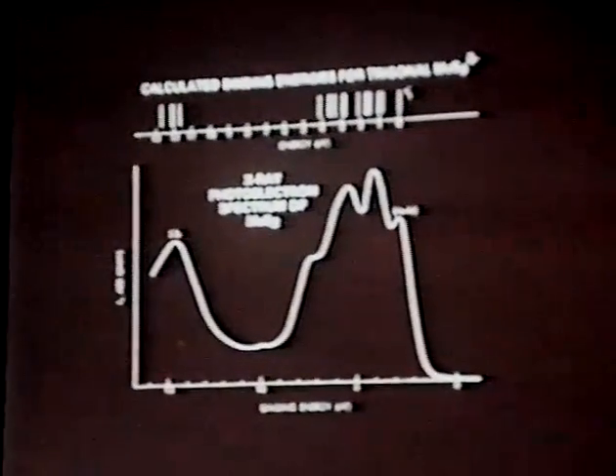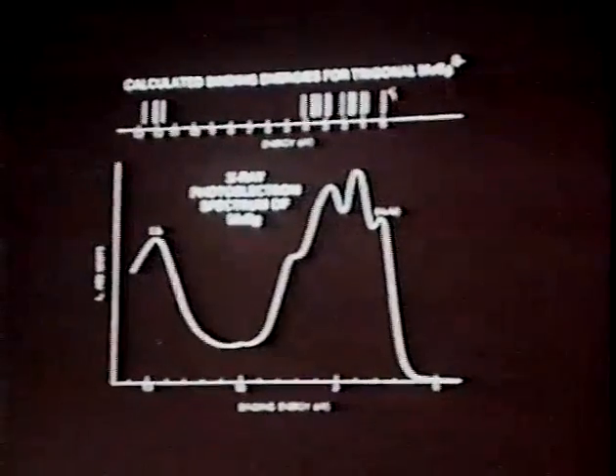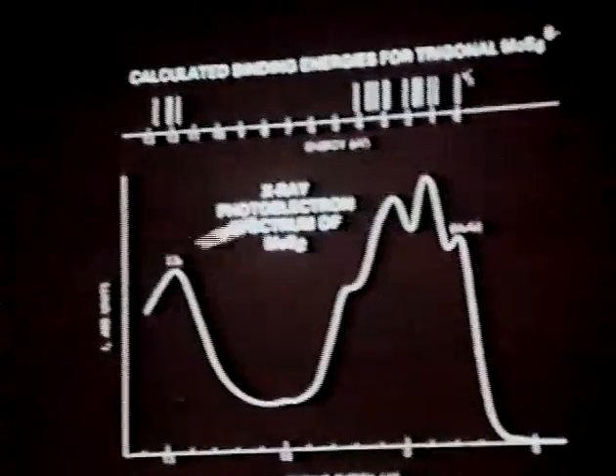This is the XPS of a molybdenum sulfide catalyst. When we do the theory, we try to measure some property like XPS, because one point I glossed over was that molybdenum sulfide is in fact not octahedral, which is the calculation we did—it is trigonal prismatic. So when doing each calculation, you extend the cluster, do the proper coordination, and compare the results by scaling the orbitals on top of the XPS and assigning them to see how well you're doing.